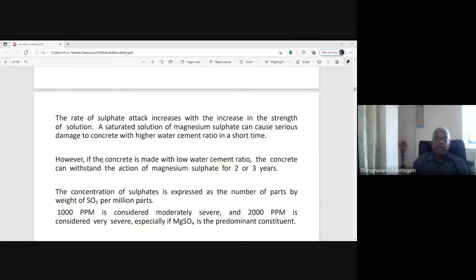However, if the concrete is made with low water cement ratio, the concrete can withstand the action of magnesium sulfate for 2 to 3 years. So magnesium sulfate is one of the chemical attacks on the concrete in the chemical industries. So if you want durability of the concrete, then you have to go for low water cement ratio. Otherwise, if you adopt higher water cement ratio, within a very short time, say after 6 months or 1 year, the concrete is completely disintegrated and deterioration takes place. The concrete has no durability, lack of durability.